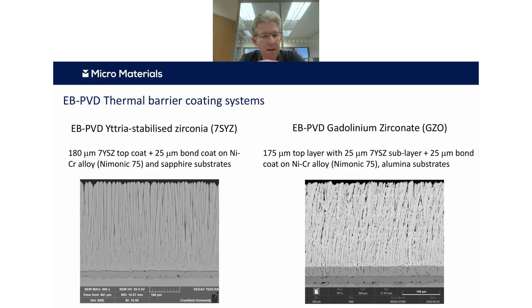So you can see there from these images that these coatings have a very interesting microstructure, and you have this very columnar structure. They both have some porosity, both within the columns and between the columns, and this adds to their strain tolerance. It's one of the reasons why these E-beam coatings are used in these demanding conditions in the engine.